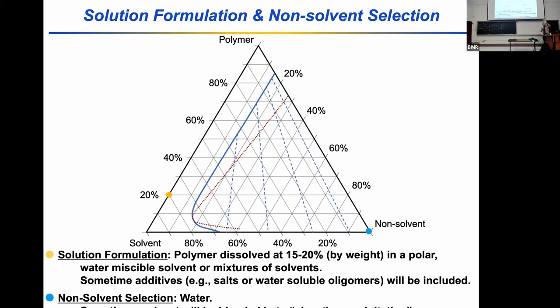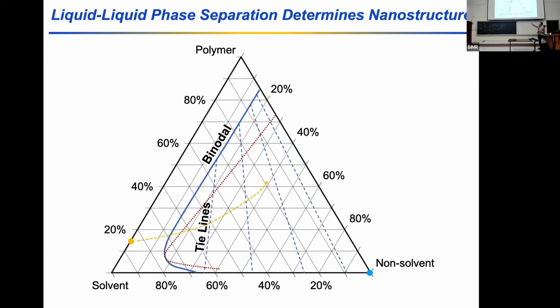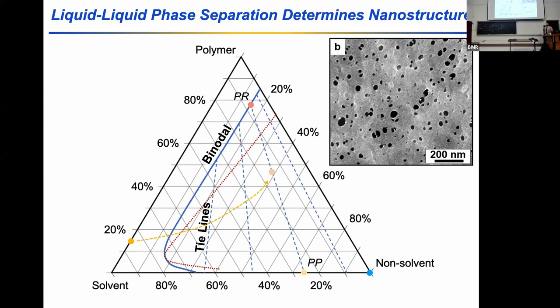And so then when we plunge that cast solution into the non-solvent and we have that solvent-non-solvent exchange, we begin to have mixture and we move into that two-phase region defined by the binodal. Let's say we land on this particular tie line, then we would phase separate along the tie line to form our polymer-rich phase on the top portion of the binodal line and our polymer-poor phase on that bottom edge of our triangle. And it's that polymer-rich and polymer-poor phase that then forms the nanostructure of our membrane.